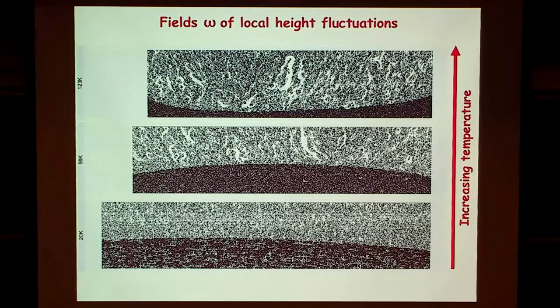If you only see a single valued height, then you just get this drop where there's an overhang. Depending upon whether you analyze the full surface or just the highest point, you get different scaling exponents in that last regime. Presumably you can't see the overhangs in this, but it would be very similar behavior there, where the crossover length scale in the interface problem depends upon the size of disorder or the size of stuff in the sheets. Perhaps if there were micro cracks forming ahead of the crack front, the way you showed in the first slides, that would set this lower length scale or be related to your lower length scale. Is there any evidence, if you look, that that's true?